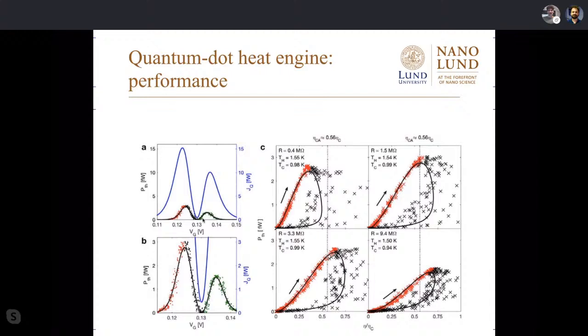The dots are again measurement. The black line is the corresponding theory prediction. The blue line is the calculated associated thermal current through this resonance. We cannot measure that, we can only predict it, and saying that the quantum dot behaves nicely according to theory, we believe that this thermal current is also true.